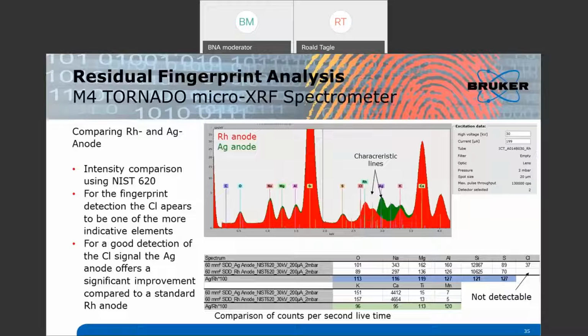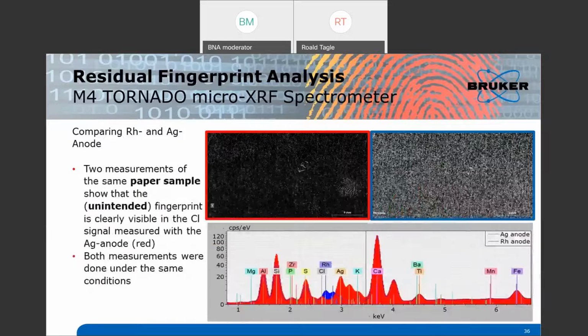So you would require a much higher counting time, and still your limits of detection will be much higher. So you will not be as good as you are with a silver anode, which has two advantages. One, not overlapping, and second, sitting in the sweet spot of the excitation edge of the element chlorine.